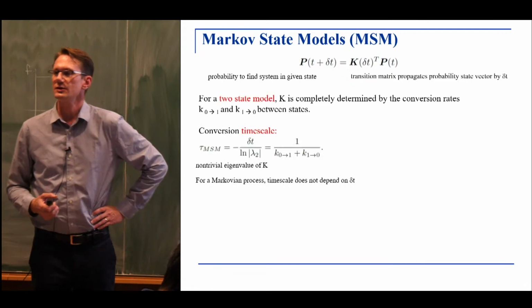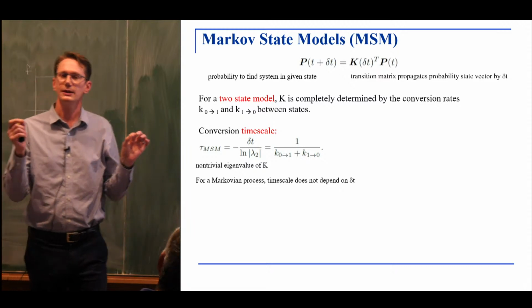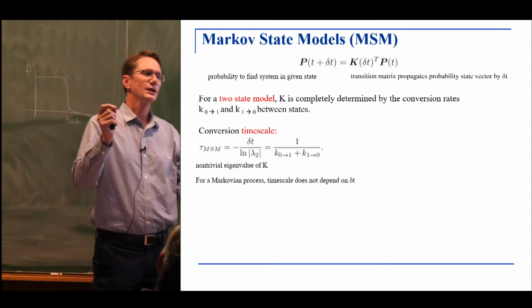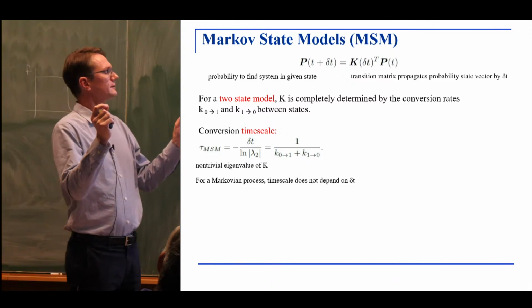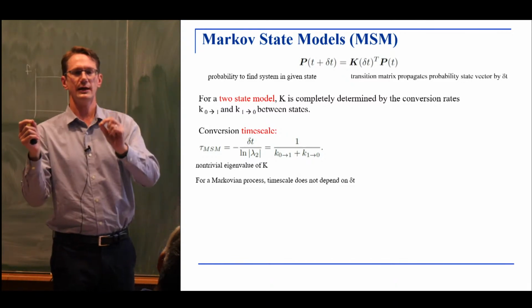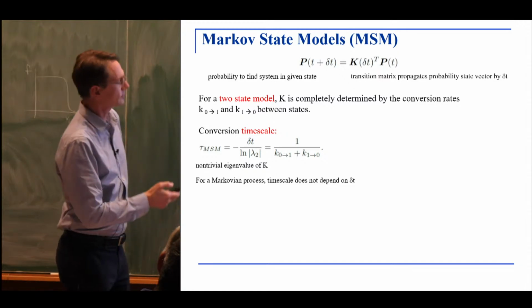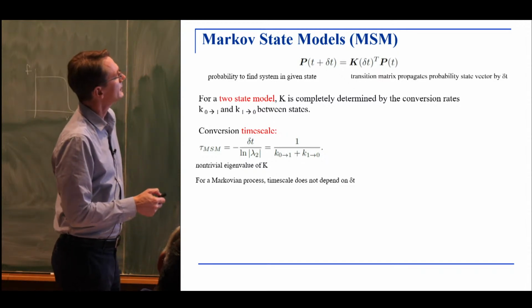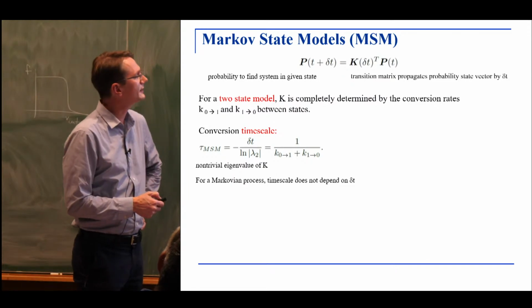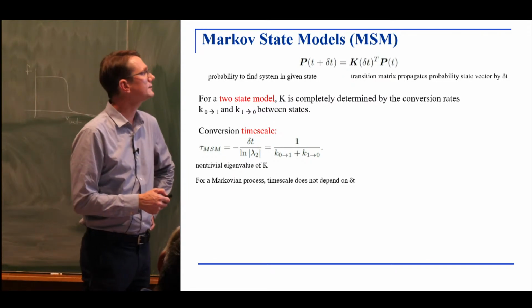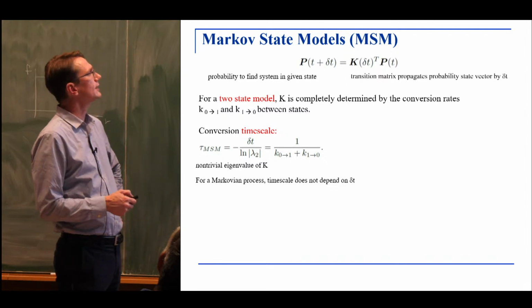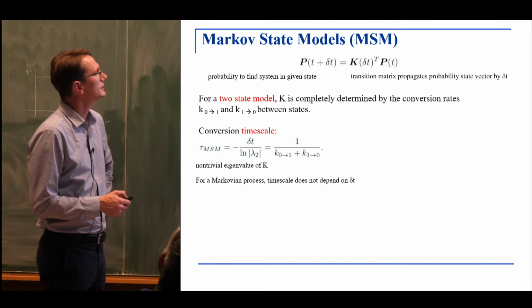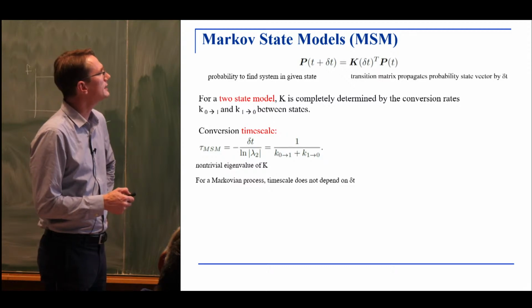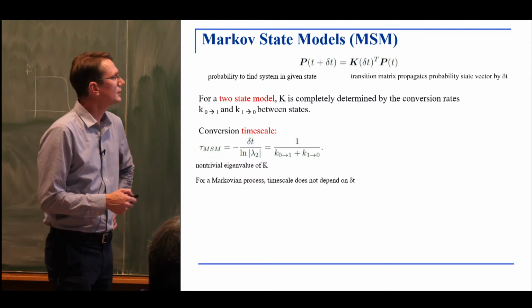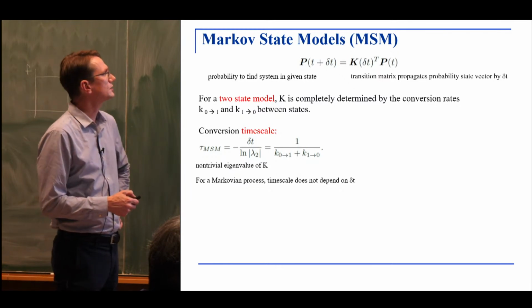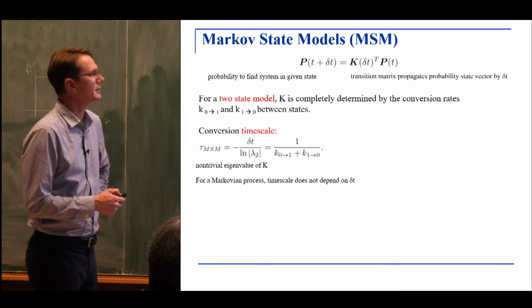Now, the simplest case that's conceptually easy to understand is a two-state model. So we have state 0 and state 1. The only information that we then need is the transition rate to go from state 0 to 1 and back from 1 to 0. Those are the only non-trivial entries in that matrix. The total conversion timescale is just the reciprocal of the sum of these rates, and one can also obtain this from the non-trivial eigenvalue of this matrix. And you see here that it depends on delta t, but as Andrea pointed out, for a Markovian process, there should be no memory, so then the timescale should not depend on this particular time.